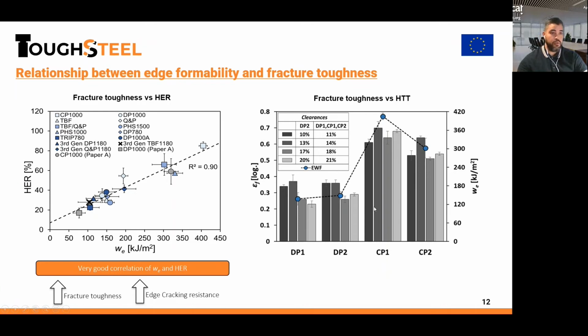However, when we look at tougher steels with greater fracture toughness, this trend is not so clear. So it's evident that edge quality is important, but the tougher the material, the higher the fracture toughness, the more able the material is to resist the different damage induced during shearing or punching.